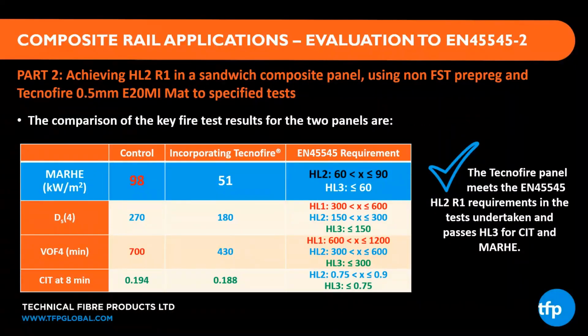In the second part of the project, the same procedure was repeated, but this time on a sandwich panel using the same non-FST rated prepreg. In this case, the control panel gave a MARHE, the maximum average rate of heat emission, result of 98. So better than the stage 1 monolithic panel, but still a high heat release rate. And again, by simply incorporating a 0.5 millimeter layer of Tecnofire E20MI, the maximum heat release drops to 51, an improvement of 48%, or pretty much by half.